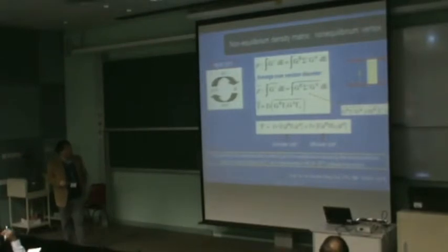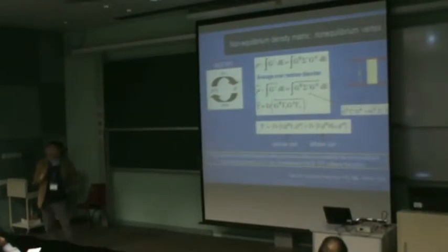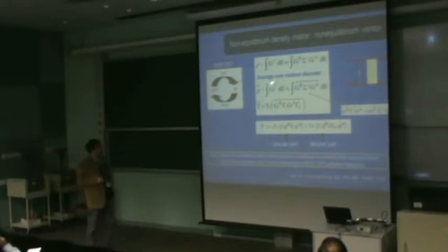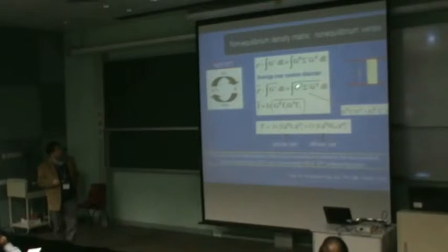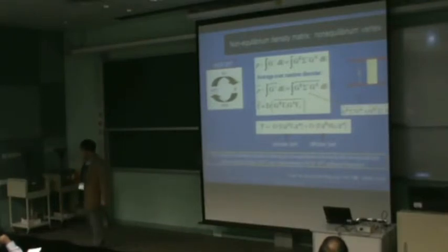What is really not known is how you do this at non-equilibrium. So essentially we have to do a bit more. The average density matrix has to be calculated by averaging over this non-equilibrium Green's function, and that is something new that Yuki did. Basically this correlates your forward propagator with the backward propagator. So you have to calculate some extra vertex correction to this Green's function. The important thing is that this correlated average is not equal to the average multiplication. By doing this average, you are going to get two terms automatically, theoretically. One describes the specular part of the scattering, the other is the diffusive part of the scattering.